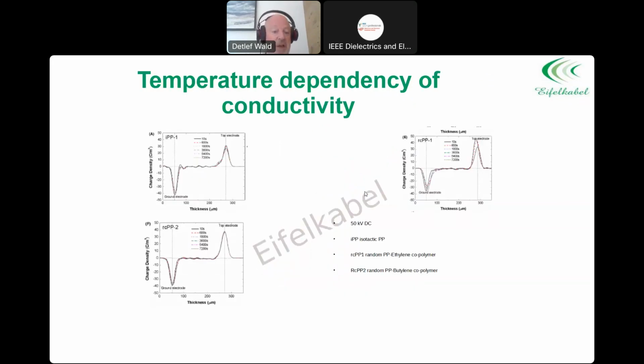The conductivity, and I fully agree, I hope this is very difficult to see depending on what screen you have. The thermal conductivity of the material using different polypropylenes, other polypropylene compounds, an isotactic polypropylene, and then it's compared with a polypropylene ethylene copolymer, polypropylene butylene copolymer, and you're getting different conductivity, the charge density. It could not be conductivity. Sorry, I have to correct myself. This is space charge measurement. I'm very sorry about that.